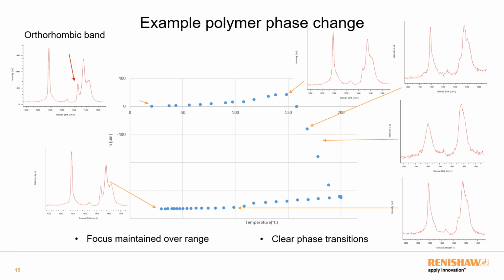At the same time, I collected the Raman data, so we can see here this is the initial data point. We've got the orthorhombic band, which gives an indicator of the phase. As we heat the sample up, we can see we've generally got the same spectrum. It's getting a bit hotter, so the peaks are broadening out and we're starting to lose some of the crystallinity. As we go above 150 degrees, here I've got a point around 170, you can see that this orthorhombic band's starting to decay. By the point we get a bit further, you can see it's gone in its entirety, so we now just have liquid. This continues, we let the sample cool down. As it cools and recrystallizes, we get the band back again, very similar to the above. And then we let it go back to room temperature and we have a very similar spectrum to the above. So what I really want to show you here is we're able to track the changes of the material even though it's moving massively in this temperature cell. And this is something which you really need this sort of fast, quick autofocus technique to do.